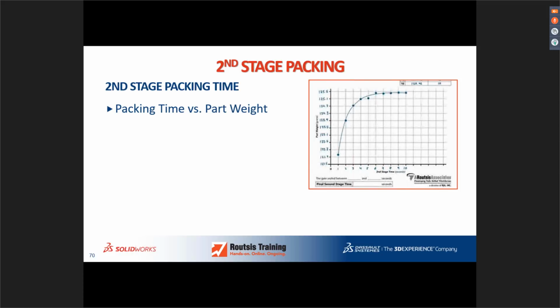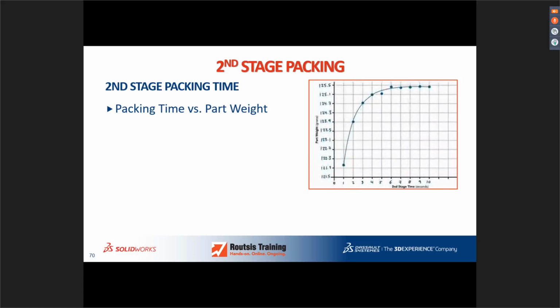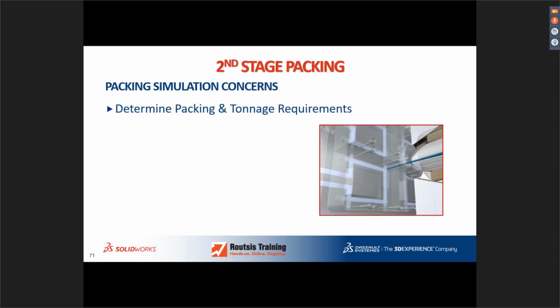And what's important is this: we'd like to determine packing time versus part weight. If you look at the right-hand side of that curve, you'll notice how things level out. We want to see that point. You can see between 5 and 6 seconds where we've got this transition. That's where we go from material flowing into the gate to flowing out of the gate. Simulation also helps us with determining packing time and the tonnage requirements so we don't flash the part.